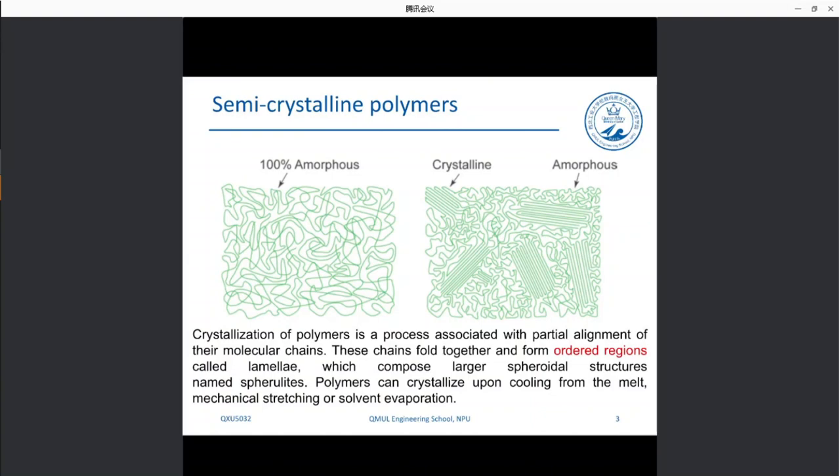The structure of polymers is very important because all thermomechanical properties of a polymer are given by a specific structural state, okay? A 100% amorphous polymer behaves completely differently in relation to a semi-crystalline polymer or a fully crystalline polymer, okay? So there are three main physical states that are characterized by specific morphologies. A fully crystalline state, which corresponds to a perfect ordering of the macromolecular entities, okay? So for a fully crystalline material, we have perfect packing, and the chains look like that, okay?